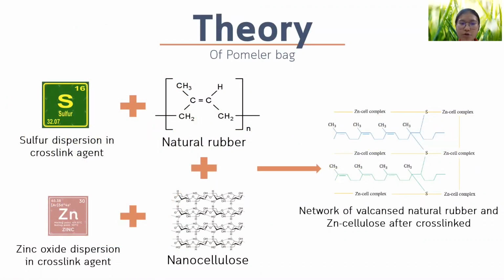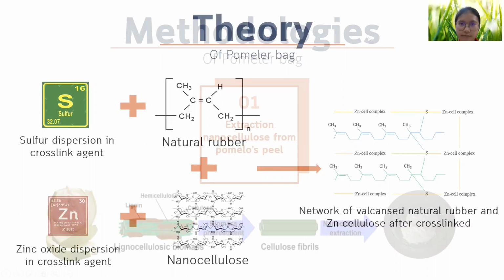Next, the scientific theory of nanocomposites. We add sulfur to natural rubber and add zinc to nanocellulose, where intramolecular hydrogen bonds could produce a large number of free OH groups at the surface of the cellulose molecules. The resultant OH groups at the cellulose surface were activated and could form complexes with zinc during ball milling. The incorporation of fillers makes interruption in the elemental process of change. When filler loading is increased, more weak interfacial regions between the filler surface and rubber matrix are formed. The resultant zinc cellulose complex diminishes the crystalline nature of the composite.